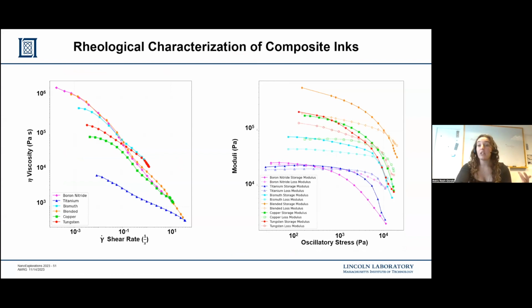So going back to the whole material science portion that was significantly longer ago than planned, we ran rheology on our ink systems. When you look at the viscosity, we have this shear thinning behavior, that downward slope. Additionally, when you look at your stress strain curves with your moduli and your stress, you have that intersection of your storage and loss modulus, showing that we have our viscous liquid flowing region in addition to our elastic region.